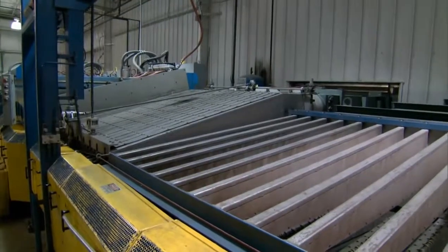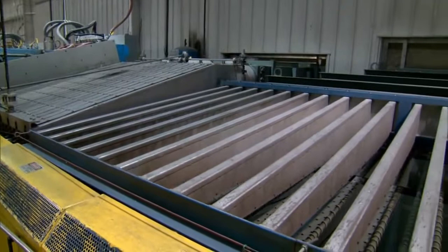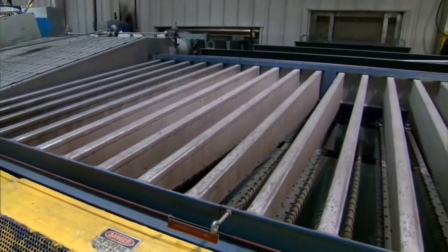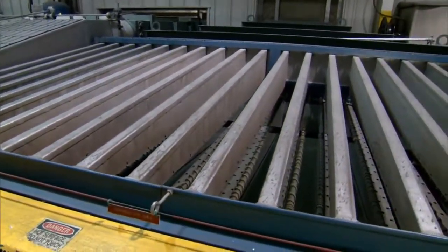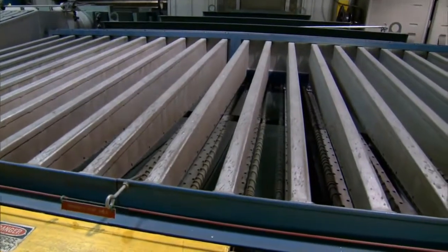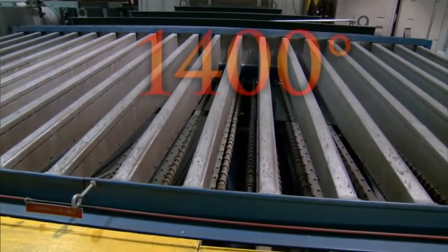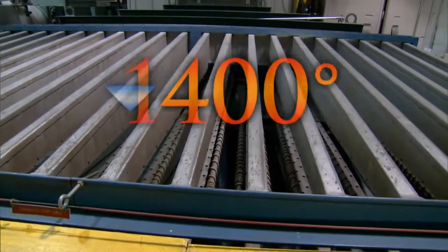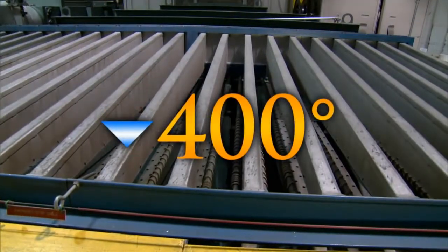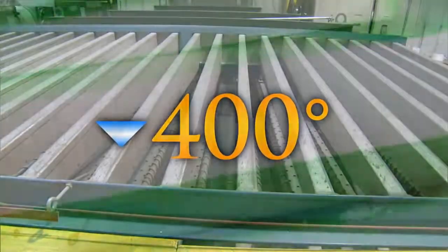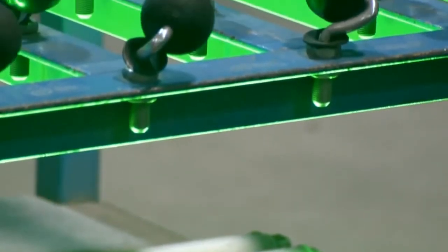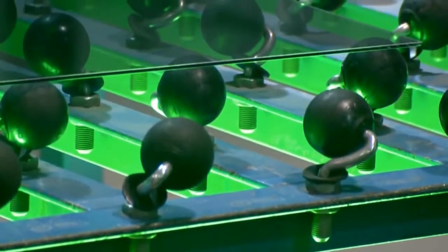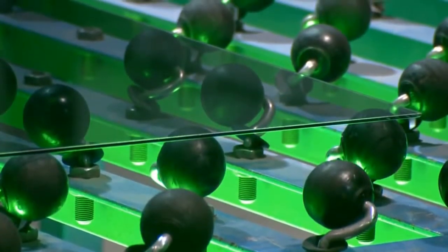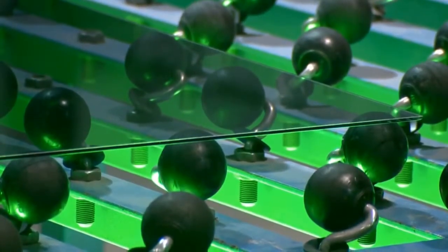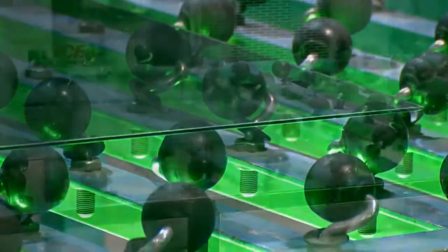Where the tempering is actually accomplished, the sheets pass through two cooling stations. At the first station, we blast the surface of the sheets of glass with cold air. This causes the glass to cool from 1400 degrees down to 400 degrees in around 4 seconds. The cooling process is completed at a second station, where special green inspection lights under the tables help operators identify any blemishes in the glass panes.